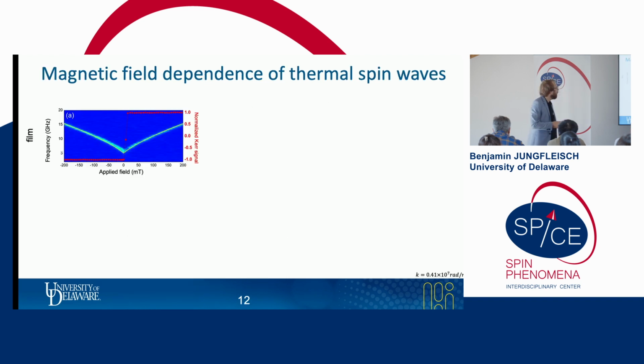So let's understand this in more detail. I'm showing here the magnetic field dependence. Before I explain the results, let me walk you through how to read this data. The color here represents the BLS intensity, which is a direct measure for the magnon population in our system. Then in yellow here, this is the result of the micromagnetic simulations. And in red, I'm superimposing the results from the MOKE measurement. So we can correlate the static magnetization with the dynamic measurements. And for this thin film, we can clearly see this Damon-Eshbach character of the mode, and we see a minimum in frequency when the film switches as we would expect.